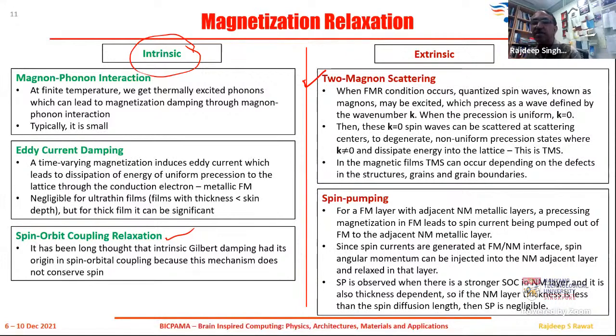As I mentioned, when we invoke this ferromagnetic resonance condition, all these spins are oscillating in unison, and their wave vector is basically zero. So these are spin waves with a k vector of 0. But if there are some scattering centers, they scatter at those scattering points. And this k=0 spin wave mode then degenerates into non-uniform precession modes, or non-uniform precession states, with k not equal to 0, where it loses angular momentum, which dissipates the energy to the lattice. And that makes it go into the relaxed state.